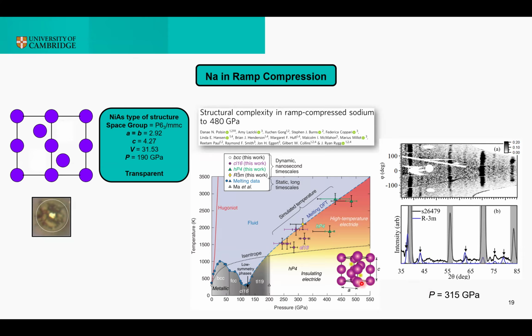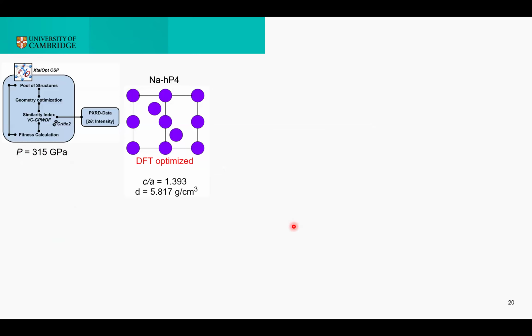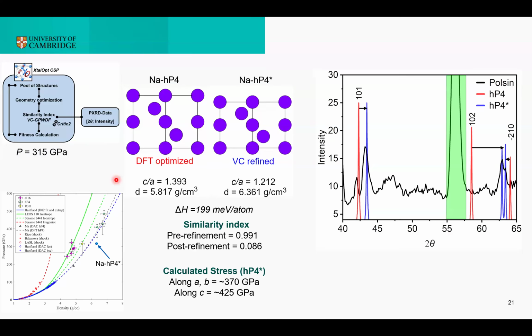However, the nature of this phase appeared to be a little bit controversial from the theoretical point of view, since it was predicted to be dynamically unstable. So I said, okay, let's see if my method can find something else from this data. With classic crystal structure prediction with DFT optimization, one would find that sodium HP4 is the most stable structure at this pressure condition. But again, this structure will not reproduce the experimental diffraction data. The surprise, at least for me, was that when I used my method, the best match was again sodium HP4. However, something was obviously different.